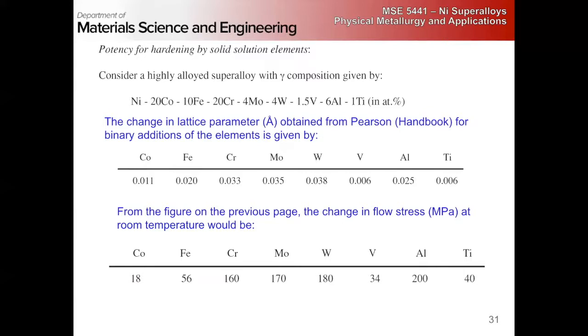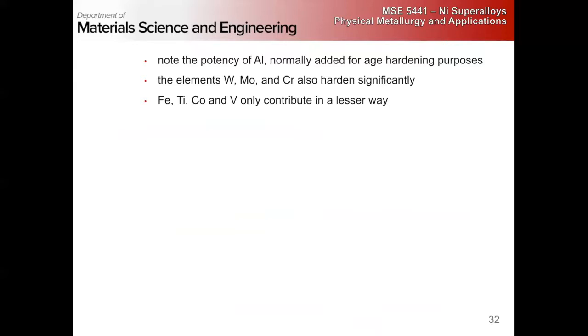So even though it's there and very potent, it is really added for its hardening purposes rather than its use in strengthening the gamma phase, right? So that means the tungsten, molybdenum, and chromium are primary solid solution strengtheners to the gamma phase. Iron, titanium, cobalt, and vanadium only contribute in a lesser way.